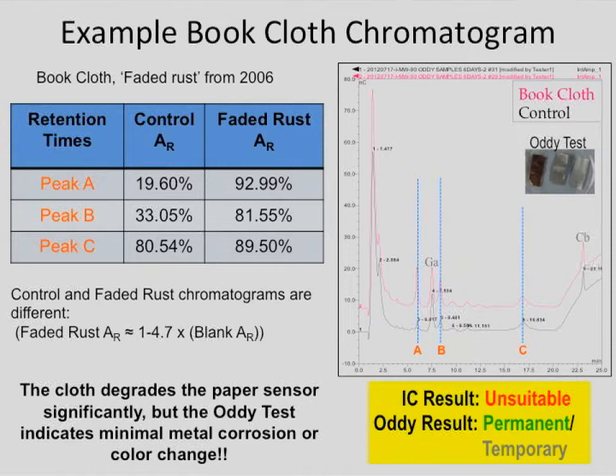So the IC result is that it's unsuitable, and the Oddy test, maybe not obvious from here, but there's some corrosion on the lead that was more significant than the control, so that was temporary or permanent, but not a lot of corrosion, so it wasn't unsuitable. We have an opposite result, where typically you might say, okay, let's use this temporarily with the collections, but by IC, I would say don't use it with the collection. This is clearly degrading the cellulose.